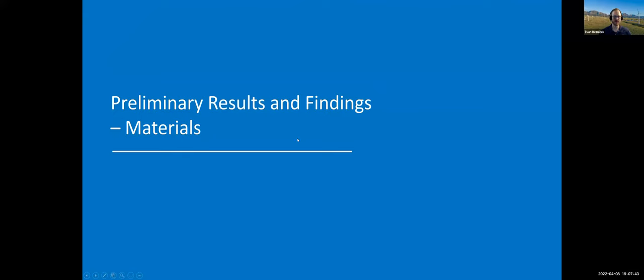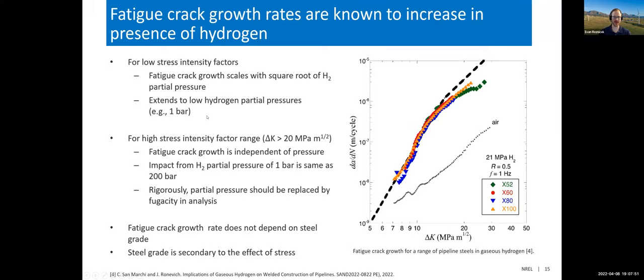So now I'll talk about a few preliminary results and findings, starting with materials. This project has only been going for about 6 months, so we've primarily been getting spooled up on models and doing literature reviews, but our colleagues over at Sandia National Lab have looked at the materials aspects of, particularly the steel material aspects of hydrogen blending quite extensively. And so we know that fatigue crack growth rates are going to increase in the presence of hydrogen.